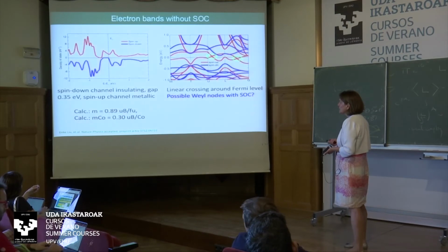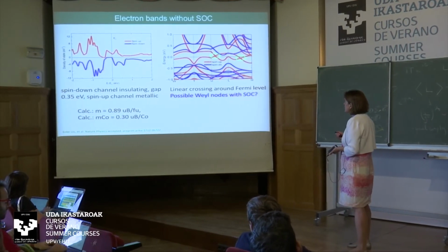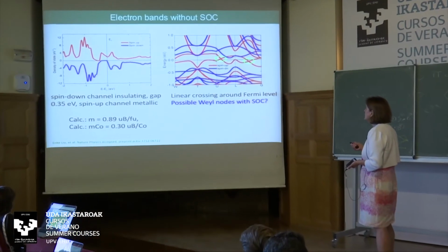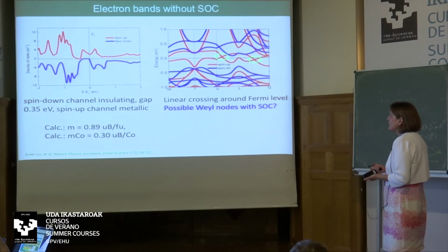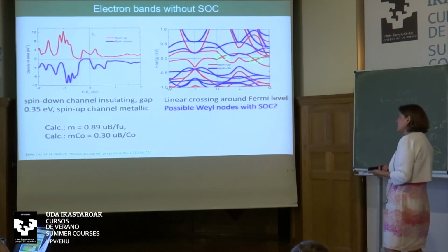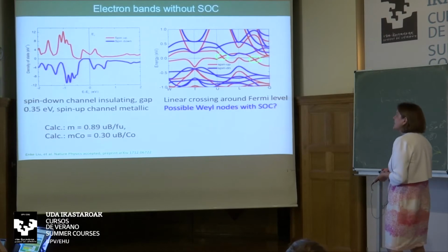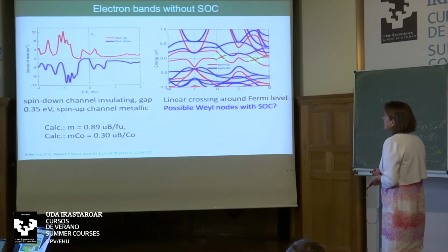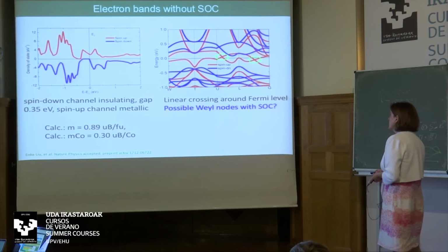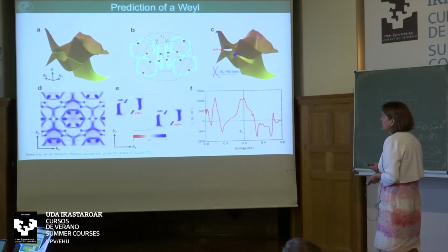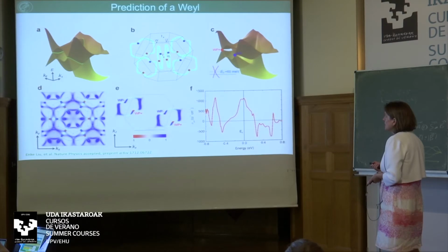So we got very nice single crystals, and this is a calculation. You have nice crossing points at the Fermi energy, and only 2 bands which cross at the Fermi energy, so it's really a semi-metal, different from all the other semi-metals in the literature, which are not semi-metals, they're all metals. Anyway, in this sense it is even a half-metallic ferromagnet, because there's a much bigger band gap in the blue states compared to the red states. And if you apply spin-orbit coupling and a magnetic field, you can open up the lines to Weyl points, which are very close to the Fermi energy.